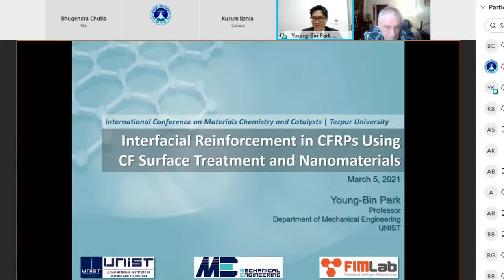So for instance, if you look at the SEM images below, these are very representative examples of the weak interface between the fiber and the matrix. In this case, we see a clear separation between the fiber and the matrix. And in this case, we have observed fiber pullout. Fiber pullout is a very common failure mode that is observed in a composite where the interfacial bonding is very weak. And also here you can see a very clean separation between the resin and the fiber, which also is evidence of weak interfacial bonding, and same thing here.